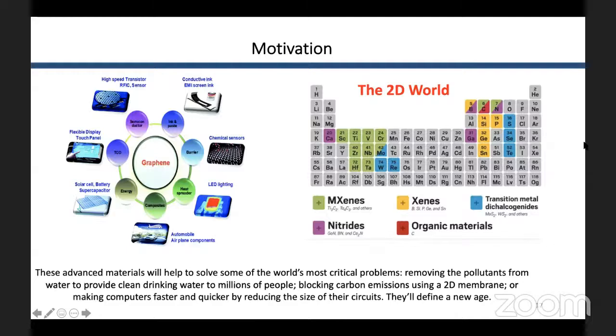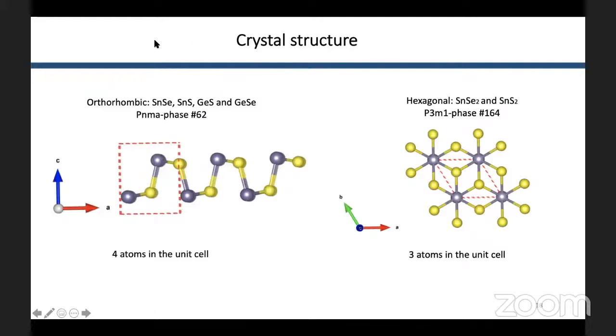And in this study, I worked with 6 materials, 4 of them with orthorhombic crystal structure, and 2 of them with hexagonal crystal structure that you see here in the figure. And we calculate all of the thermoelectric properties: Seebeck coefficient, electrical conductivity, power factor, electronic thermal conductivity, and lattice thermal conductivity.